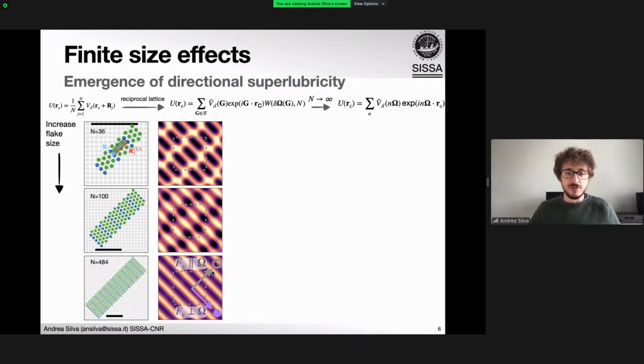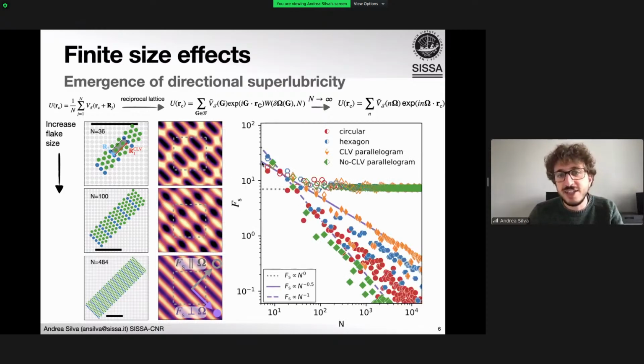Now we can go back to a bit more friction and measure the friction along the two directions, parallel to the valley or perpendicular to them. What we find is that the friction scales very differently. We have a finite friction per particle, so it's constant, perpendicular to the valleys, while along the corridor, as the size increases, it scales sublinearly.